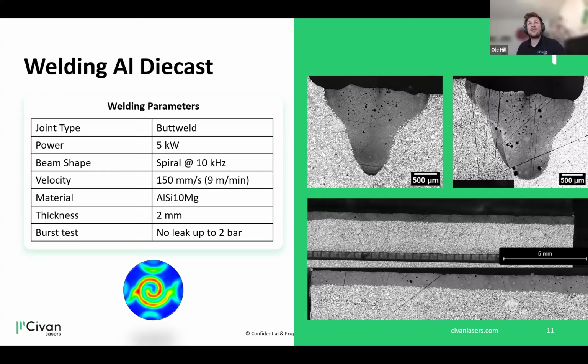Just a note that casting for laser welding is actually a good way of casting because you can avoid large, big walls, which are an issue for casting as well as welding. In this case, we achieved a 2 mm deep penetration, but we have done anything between 0.5 and 5 mm of penetration for aluminum die cast. And once again, in the velocity range of up to 10 meters per minute, sorry.